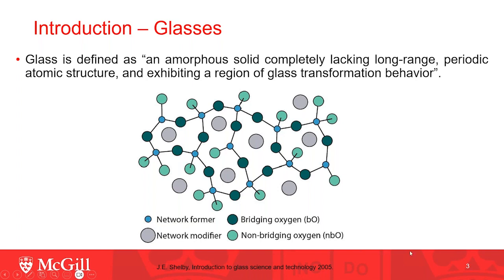Glasses are in the subfamily of ceramics and are characterized by their amorphous nature — they lack crystallinity, that is long-ranging periodic arrangement. Glass also shows a range of glass transition behaviors. Glass transition temperature is the temperature above which solid glass begins to behave as a viscoelastic material. It can be used to indicate the bond strength and network connectivity of the glasses. Glasses are often made of oxides including network formers and network modifiers. The network formers form the highly cross-linked network of chemical bonds, while network modifiers disrupt the network connectivity and influence the final properties.